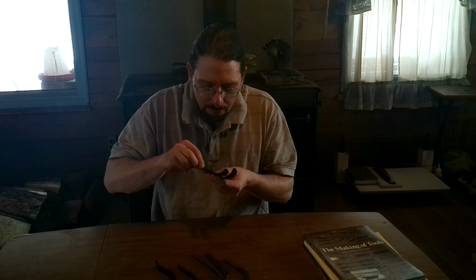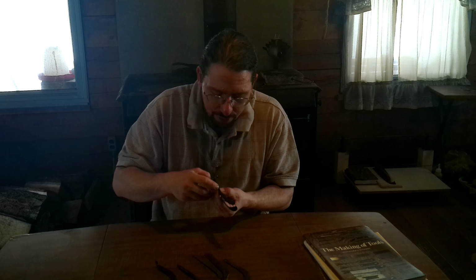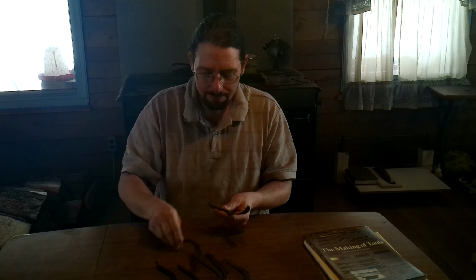So a little piece of mill scale got hammered in, or a little piece of rust or a pebble that got stuck into the rust, or something was there that then popped out when it quenched. So you'll see those after the quench that you don't see before it. Two of these have some small inclusions. This one has one right here where it's really thick. I know for sure I can file that one out. I think I can file this one out. It's getting a little thin right in that spot where it is.